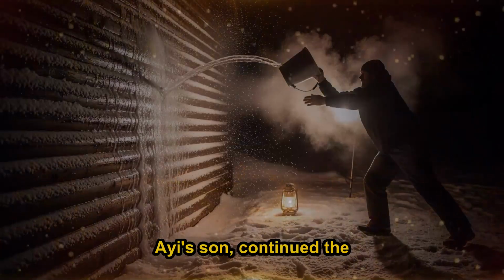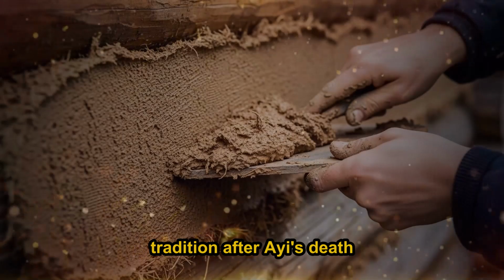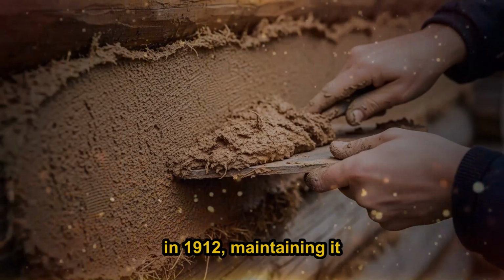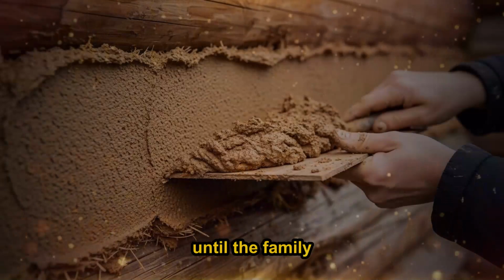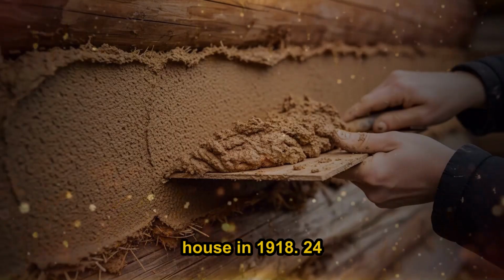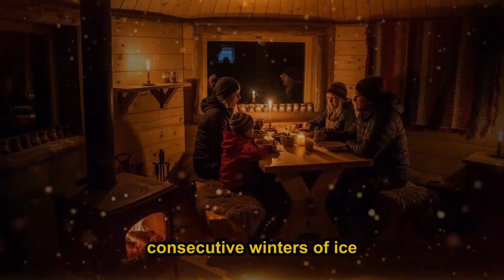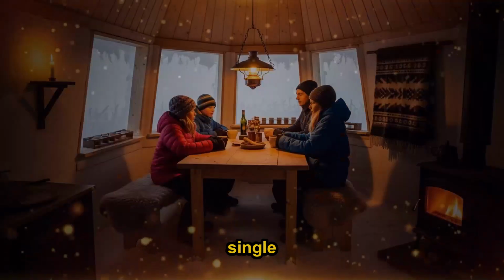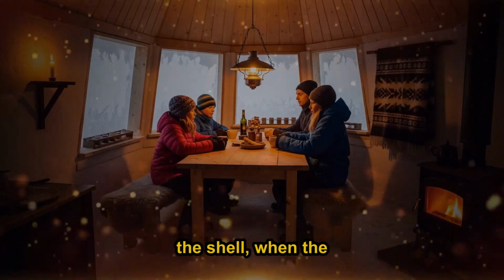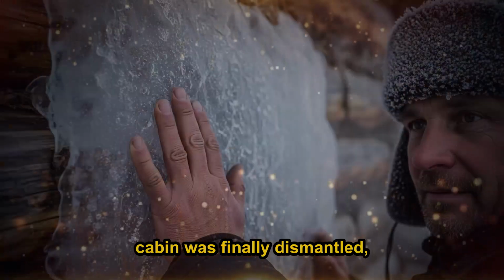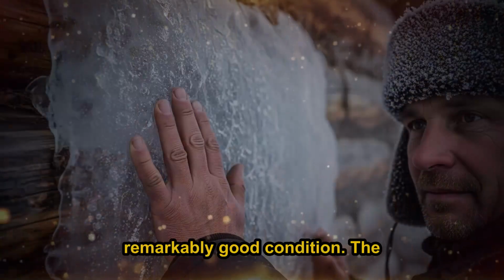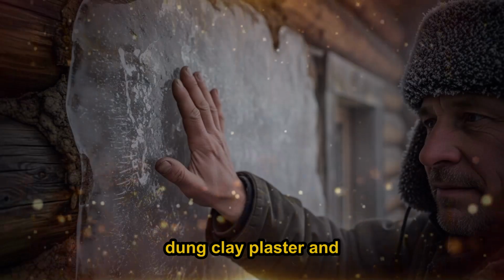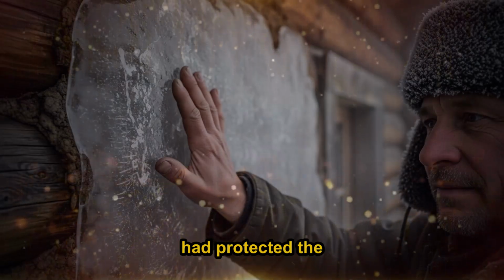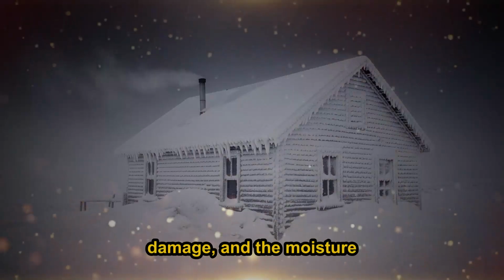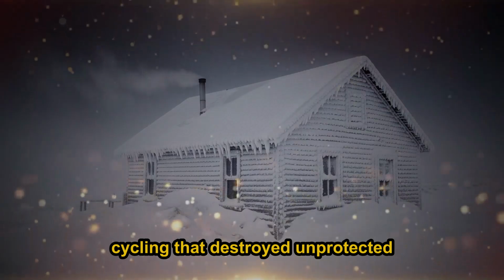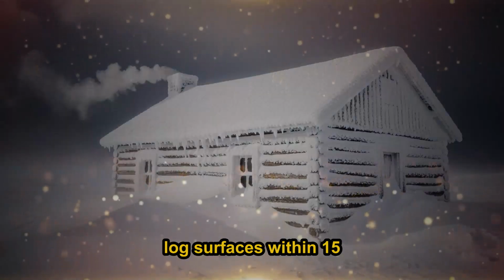Bolot, Ayi's son, continued the ice shell tradition after Ayi's death in 1912, maintaining it on the original cabin until the family built a new frame house in 1918. 24 consecutive winters of ice shell application on a single building. The logs beneath the shell, when the cabin was finally dismantled, were in remarkably good condition. The dung clay plaster and the annual ice coating had protected the wood from weathering, insect damage, and the moisture cycling that destroyed unprotected log surfaces within 15 to 20 years.